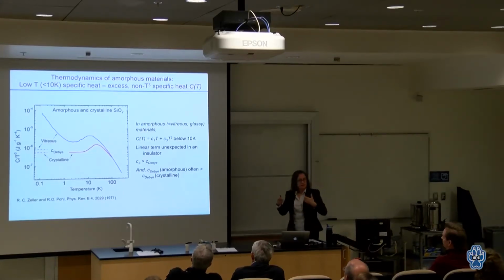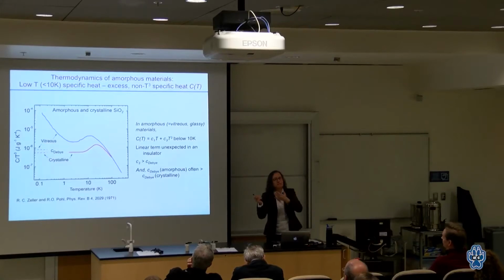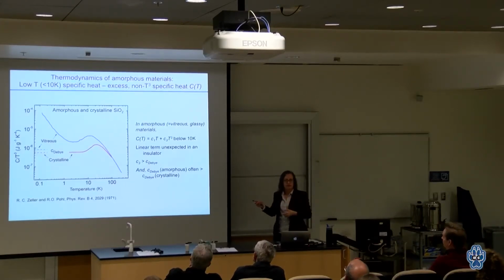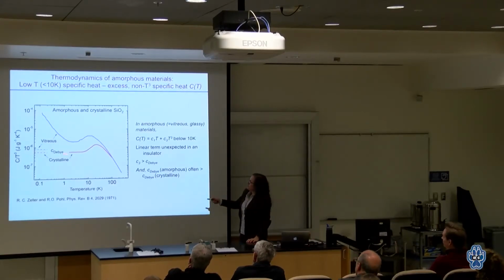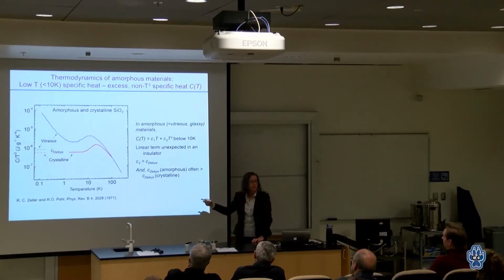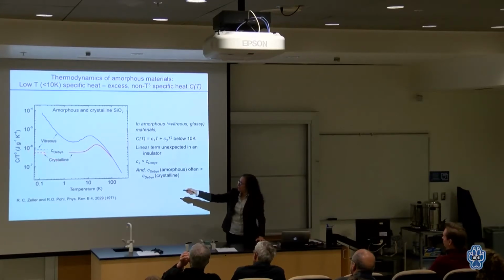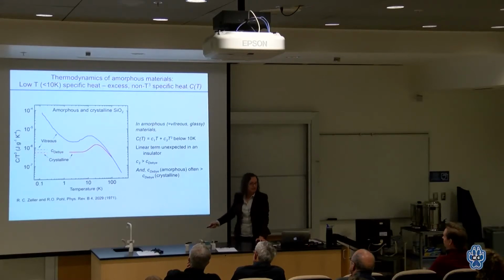the low temperature heat capacity of a solid is supposed to look like gamma T plus beta T cubed, where the gamma T is the metal term, for those of you who know this, and the beta T cubed is due to the phonons, the lattice. So an insulator should only have the beta T cubed piece. And indeed, Chris, this is the plot, the red is the plot for crystalline silicon dioxide. The low T part you can actually theoretically calculate if you know the sound velocity. So you measure the sound velocity, and from that you calculate the low temperature heat capacity, and that's that little dashed red line. And indeed, you can see the crystalline material is coming in very nicely to that value.